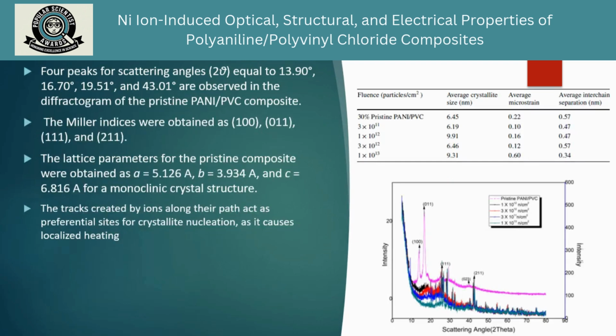Another work done for confirming the structural changes was the XRD analysis of the samples. In that case, four peaks for scattering angles 2 theta equal to 13.90 degrees, 16.70 degrees, 19.51 degrees and 43.01 degrees are observed in the diffractogram of the pristine PANI-PVC composites. These peaks correspond to the Miller indices 100, 011, 111 and 211.